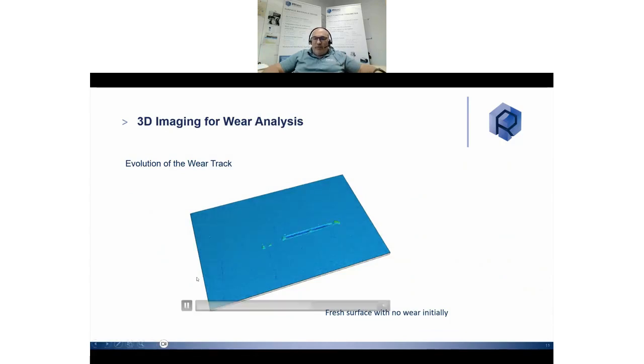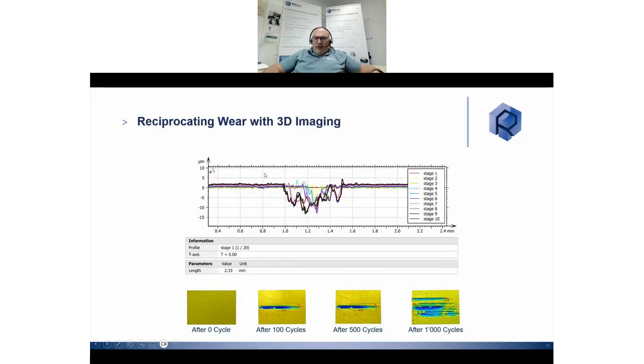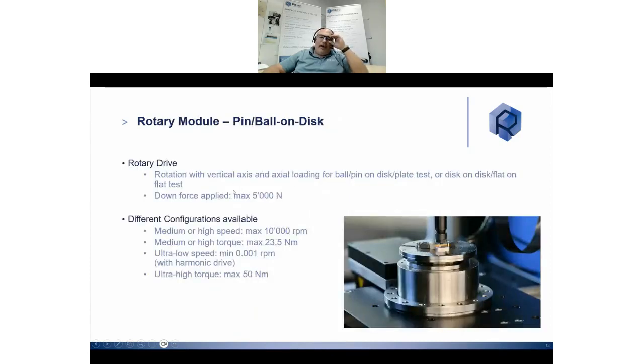You see here the increase of wear during the 150 minutes, and with the debris, with the large wear, where it's coming from, do we have hard particles? We can check really the lifetime. We can do multiple profiles in order to understand the wear rate every 10 minutes and combine on a curve to have a really related test for wear rate.